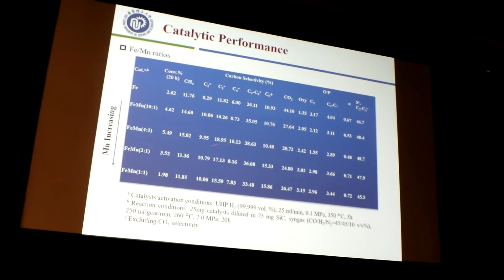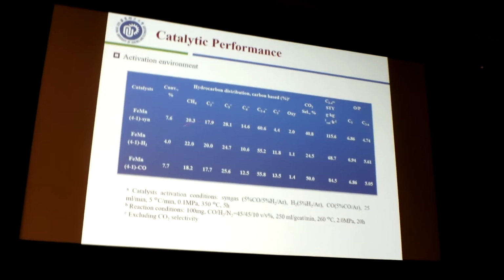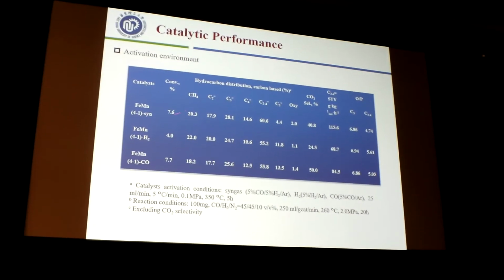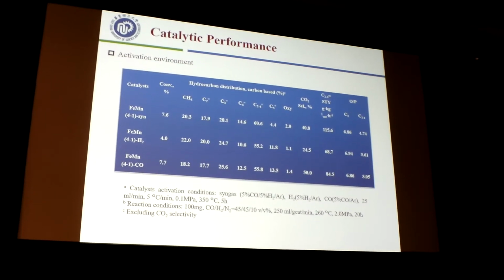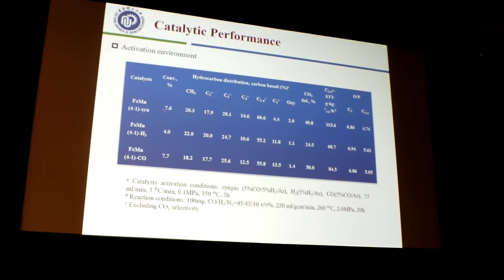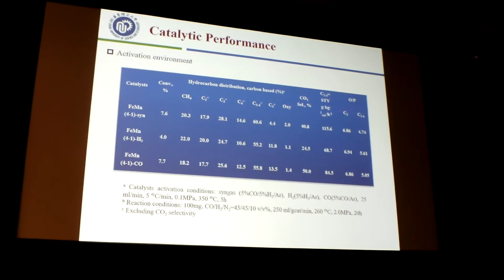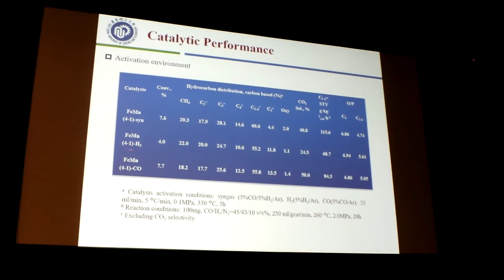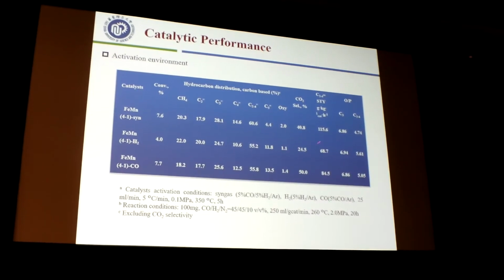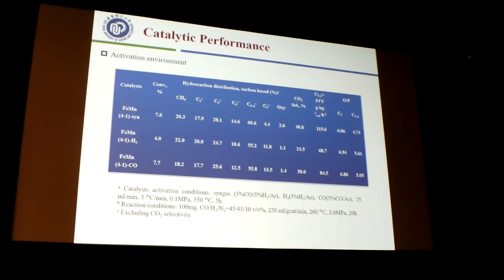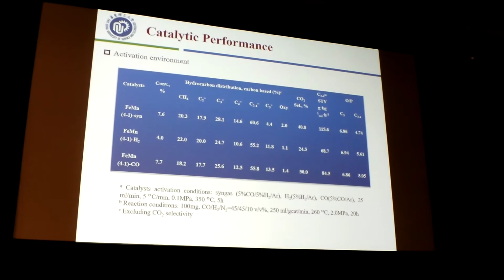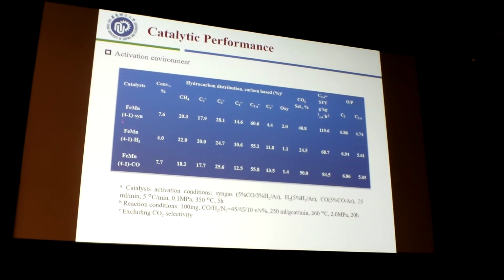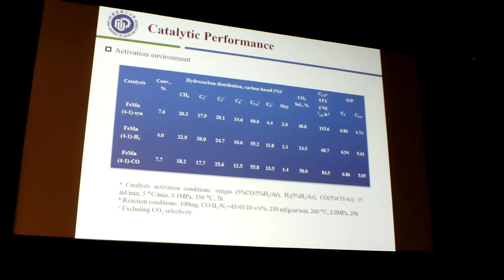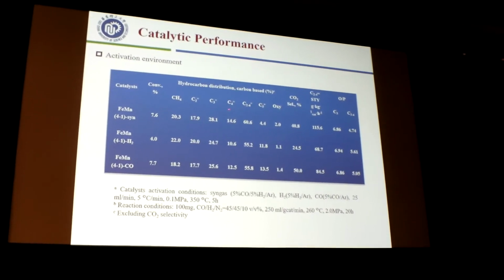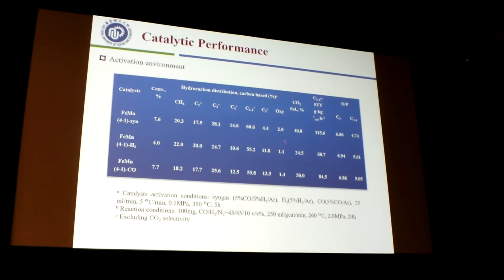since it has the highest conversion and the highest light olefin selectivity. Using this iron to manganese 4 to 1 catalyst, we further investigated the effect of the activation environment on the catalytic performance. This table shows the catalytic performance under syngas, hydrogen and CO activation environments. We can obviously see that the activity was highest using syngas as our activation environment, and the highest observed C2 to C4 olefin selectivity reached nearly 60%.